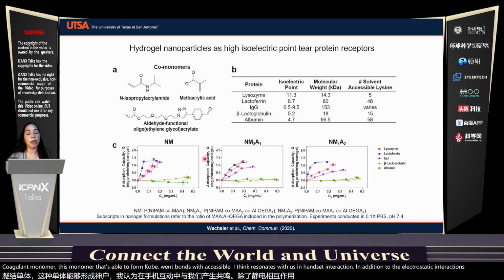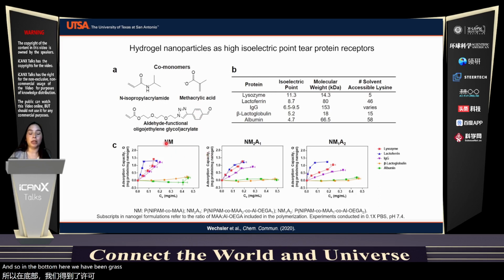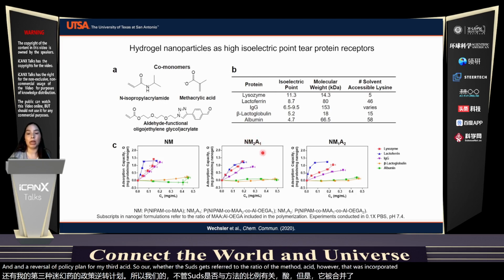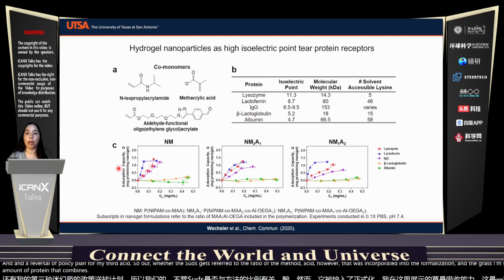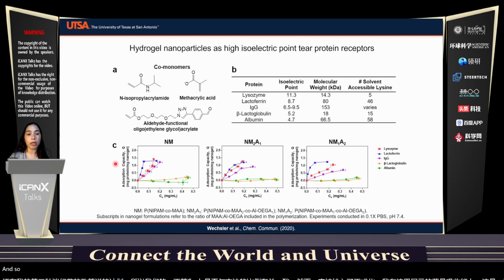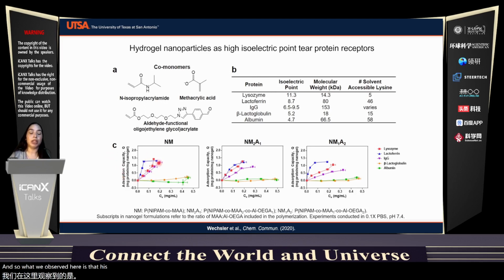And so in the bottom here, we have 3 graphs. The acronyms here, NM refers to our poly(NIPAM-co-methacrylic acid), NMA refers to the poly(NIPAM-co-methacrylic acid-co-ALOEGA). The subscripts refer to the ratio of the methacrylic acid to ALOEGA that was incorporated into the polymerization. And the graphs I'm showing here are the absorption capacity, which is a measure of the amount of protein that can bind per mass of nanogel. And so what we observed here is an increase in absorption capacity of high isoelectric point proteins.